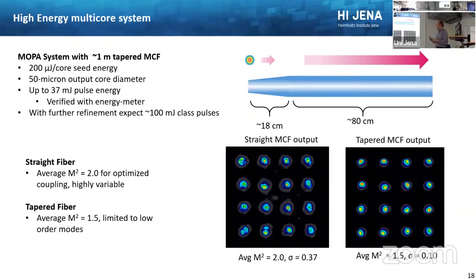And if you add a taper, that you can see on the top right side, so basically you make the fiber a bit smaller, in a small piece at the beginning of your fiber, this goes down from 50 to about 20 microns, you get better excitation at the beginning, and a lot nicer mode output profile here on the bottom right. And you can also see its M² value decreases a lot.